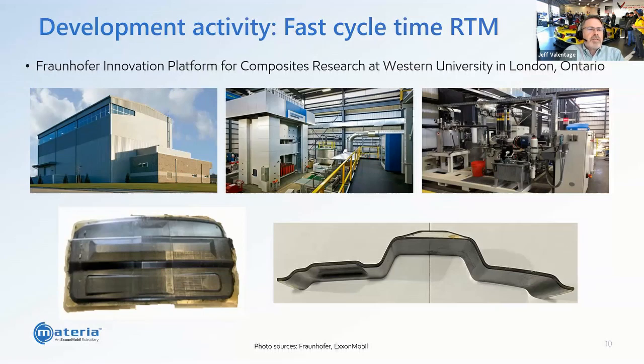And the fabrics that we've been currently working with are glass and carbon fiber. And we're looking at doing some flax fiber development in the future. Initial trials show very positive results. We were able to do a cycle time of less than 2 minutes without any optimization and using this prototype tooling. So we look at doing additional work in 2024 on this particular part.